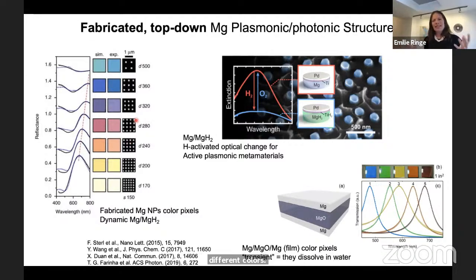But magnesium has had an appeal a bit different from the other metals, because it can do this magnesium to magnesium hydride back and forth reaction, where the magnesium hydride is not plasmonic and the magnesium is plasmonic. So you can think of it as a tunable on-off sensor for hydrogen. There are also claims that magnesium is transient as a plasmonic, meaning you could dissolve it in water and make your plasmonic material disappear.